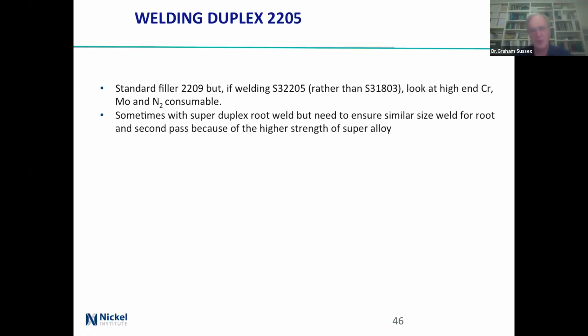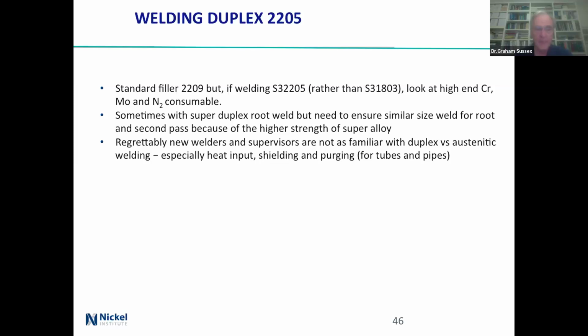Sometimes a super duplex root weld, but you need to be careful. You need to make a similar size weld for the root and second pass because the super alloy is stronger. That means if you just had the root in super duplex, then you've got something close to the inside which is not as strong. So two passes and then go back.